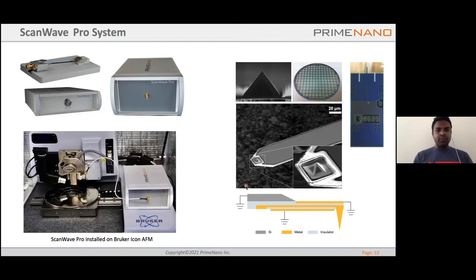These are similar in form factor with respect to the other commercially available probes, but there is one unique aspect to that: the cantilever is completely shielded. The microwaves are passed through the central metal line, and all the sides of the cantilever are shielded with metal, and the microwaves are only passing through this pyramid. And that makes the source of the microwave very tiny. With the tip apex about 10 to 15 nanometers in radius, you get sub 5 nanometer spatial resolution in the electrical properties.